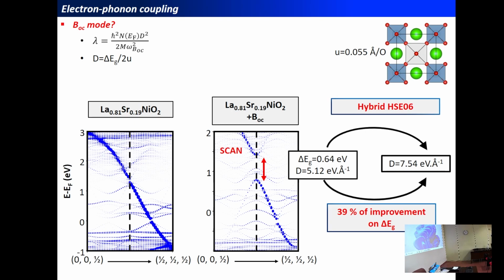So now, in these systems, like in the bismutate, we have identified a phonon that is strongly coupled to the electronic structure. Again, this is the breathing distortion. So we will restrict the electron-phonon coupling to this precise phonon mode. And therefore, we still have to compute the different contributions. So we will focus on the D term, which is the most important one.